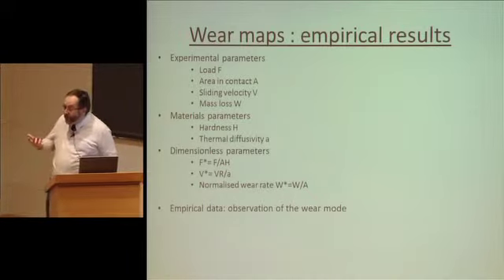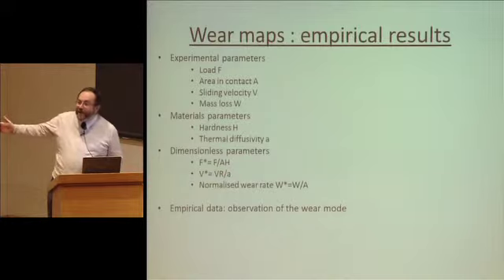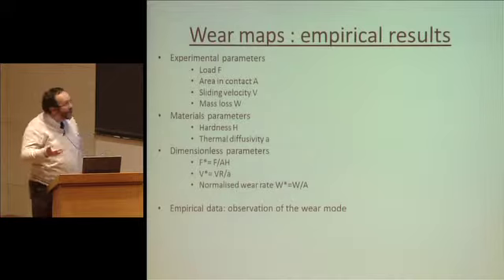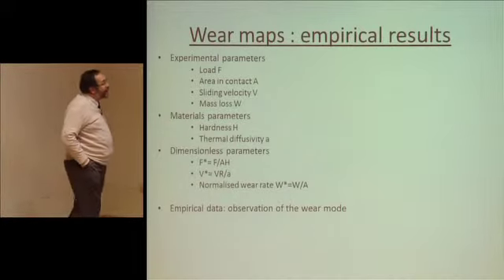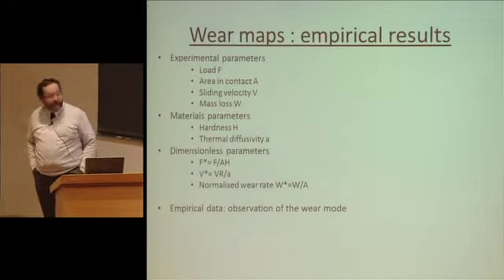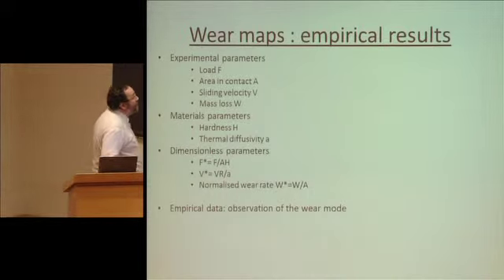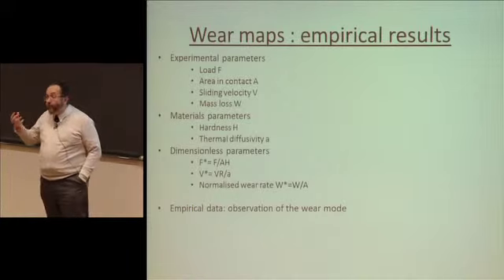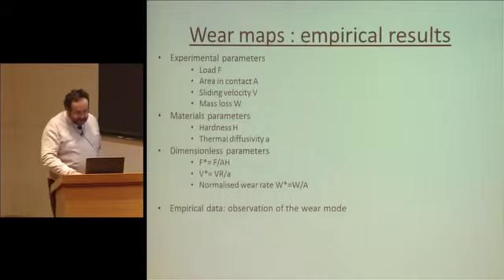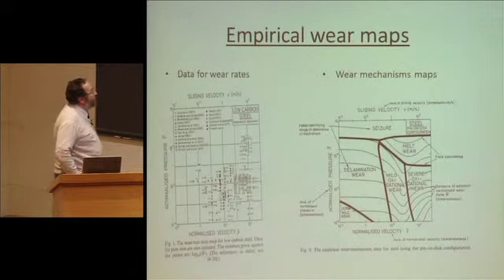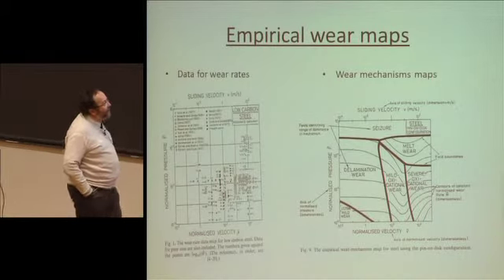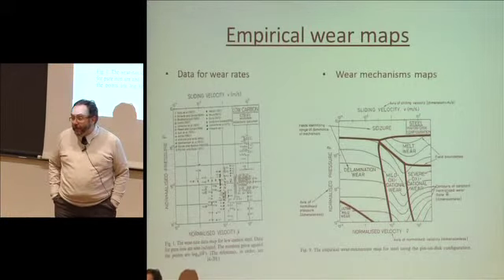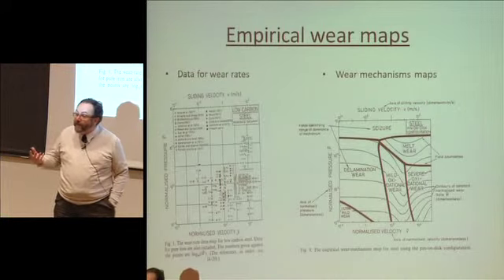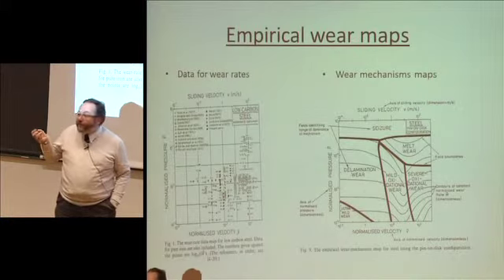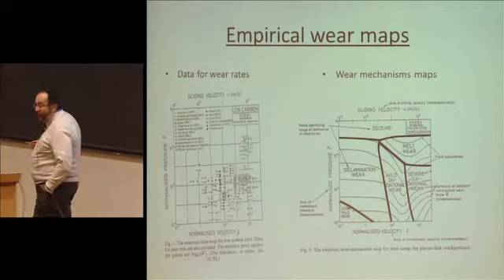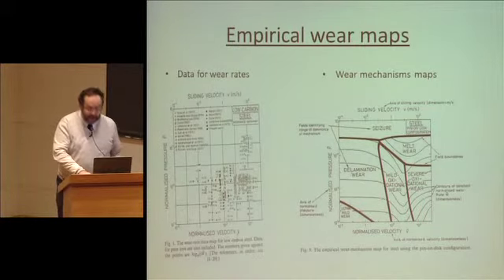Then you're going to have thermal diffusivity. You're creating heat through rubbing, which is going to diffuse across the material. It's not the ambient temperature, it's the temperature where the rubbing is happening. And that leads you to create dimensionless parameters, force characterized by F and AH, speed, characteristic speed connected to a size of the contact, and diffusivity. So the empirical data maps, you have them here. There's a whole lot of data that was brought together by Mike Ashby on low carbon steels. And to the right you have something that can actually help you to rationalize that with the dominant modes of wear. And if you want to have something that is going to let you discover what is going to happen over time, you must stay within the constraints of solicitation of stress. So how are these maps derived?